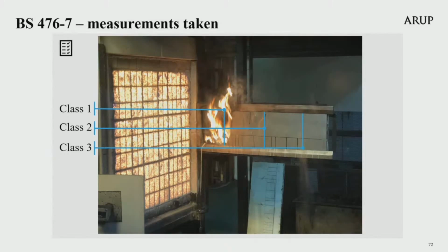Throughout the test, it is required to carefully observe the behaviour of the product and make a note of the following phenomena: flashing, transitory flaming. Observe and note other phenomena such as debris falling away from the specimen and whether it is flaming or not, any intumescence or deformation of the specimen. These additional observations do not influence the classification of surface spread of flame.